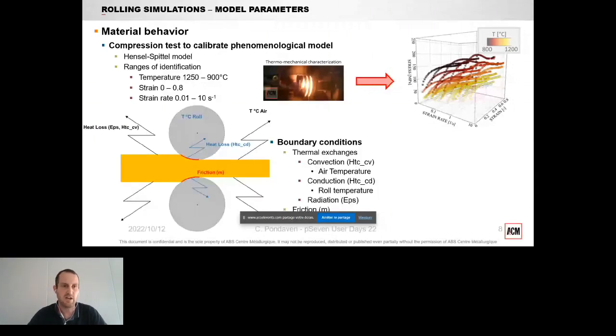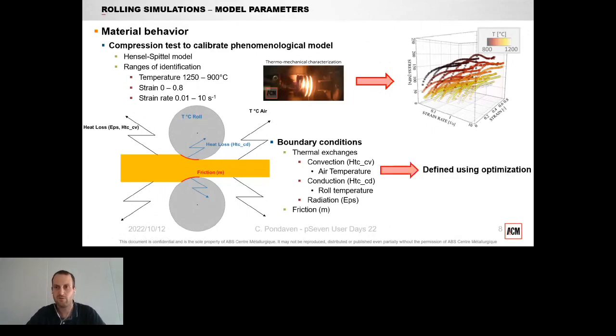We will then have to define the different boundary conditions of the model, which are the different thermal exchanges with the heat transfer coefficient of convection, conduction, the emissivity for the radiation heat loss, the external air temperature and the die temperature, and also we have to define the friction parameter. For our simulation, we use a Coulomb limited friction curve model.